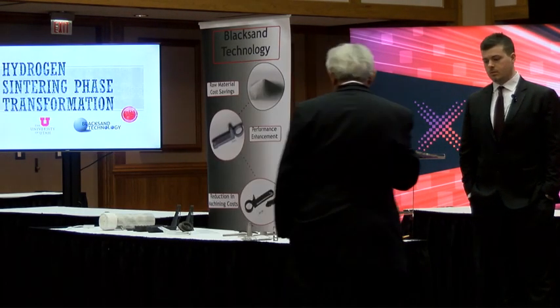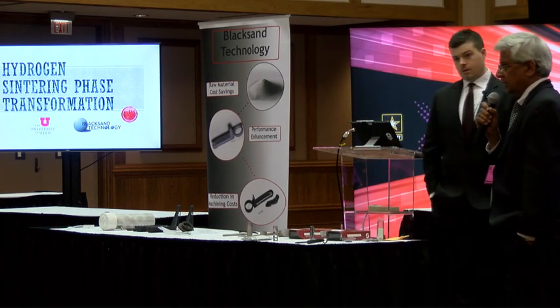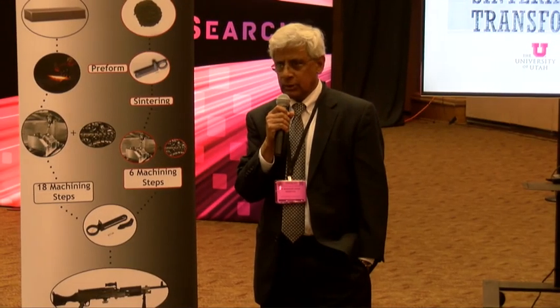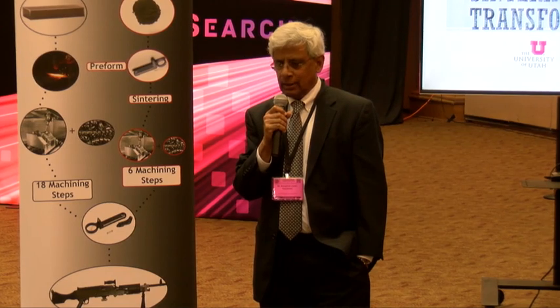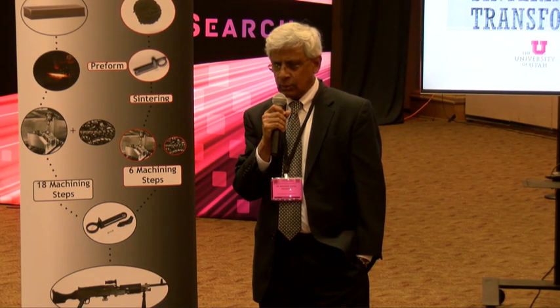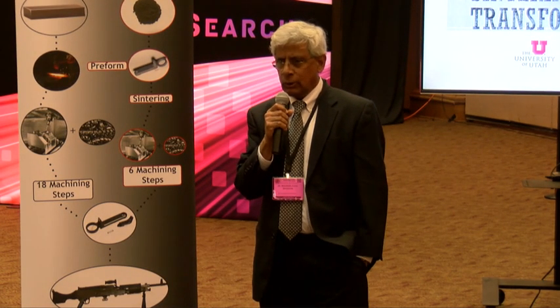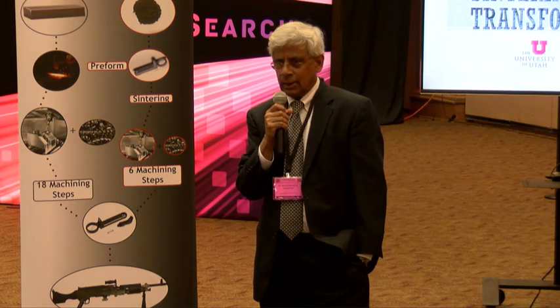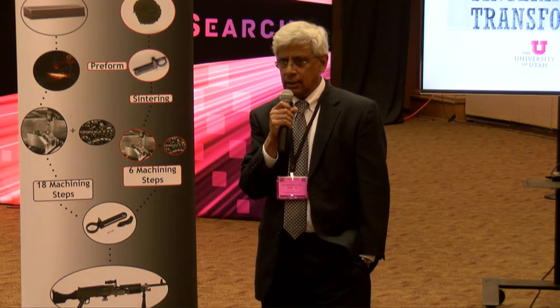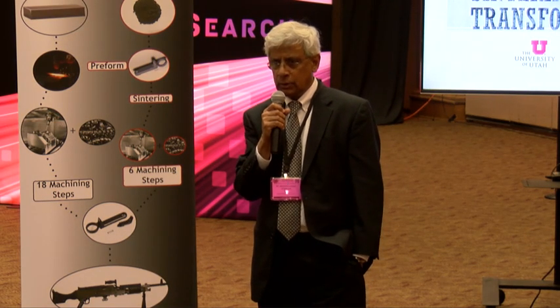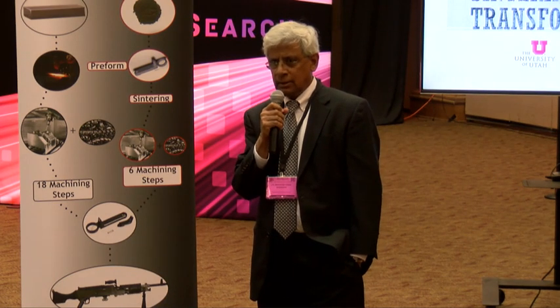So if you look at the novelty in this process, it is the use of hydrogen for sintering. If you sit and ask why hydrogen, nobody would have thought about it, because for the last 50 years all the titanium alloys are heat treated in a vacuum furnace. So the patent is really the use of hydrogen during the sintering process.